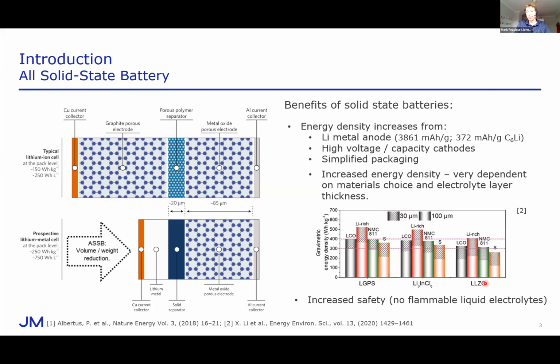In contrast, with a much denser electrolyte, a lithium lanthanum zirconium oxide, a garnet type of material, if you combine that with some of these other cathode materials, perhaps in thicker layers of electrolytes, the energy density is nearly half that. So there's a lot riding on getting the materials choices right and processing them right to thin layers. On top of that, in the absence of the organic liquids, things are much safer in terms of flammability and explosion risks.